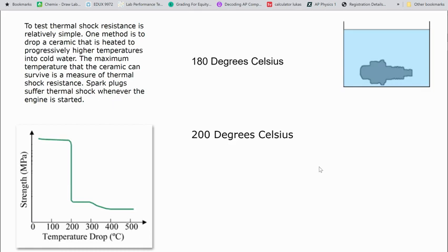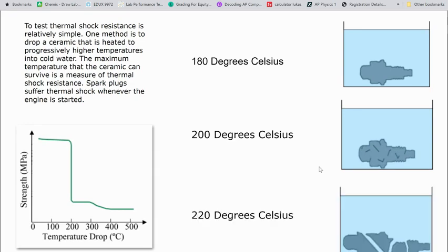And we can see with a spark plug, if we heat it up to 180 degrees and drop it into cold water, we see no signs of thermal shock. But at 200 degrees, we're starting to see that tension being relieved through cracking at the surface. And if we have a 220-degree drop in temperature, the spark plug is brittle and breaks into many pieces. And so thermal shock resistance would tell us that a spark plug can handle a change in temperature up to 180 degrees Celsius. After that, we're going to see damage to the part.